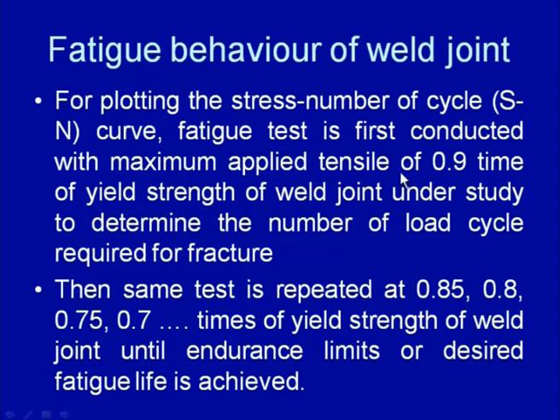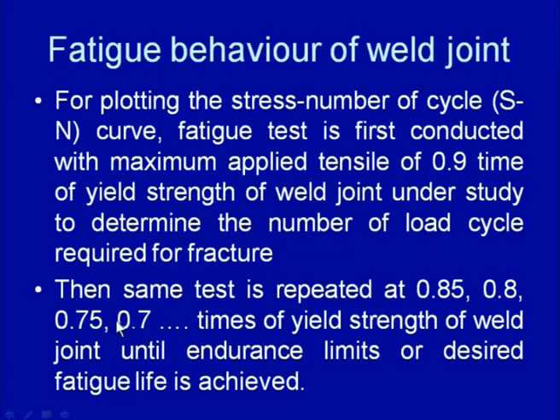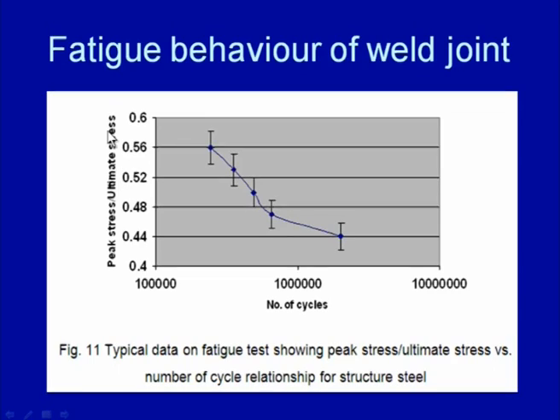The fatigue test is first conducted with a maximum applied tensile stress of 0.9 times the yield strength of the weld joint under study, to determine the number of load cycles required for fracture, and then the same test is repeated at 0.85, 0.8, 0.75, 0.7, 0.65, and like this, corresponding to the different maximum stress levels the test is conducted, and the number of load cycles required for failure is identified. Then we develop a plot, with either the stress range, stress amplitude or the maximum stress on the y axis and the number of load cycles on the x axis, to have the S-N curve. These S-N curves can be plotted on linear scales or log scales.